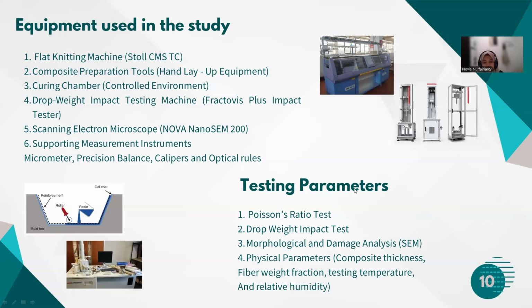And then testing parameters: Poisson's ratio test, drop weight impact test, morphological and damage analysis. And then physical parameters: composite thickness, fiber weight fraction, testing temperature, and relative humidity.